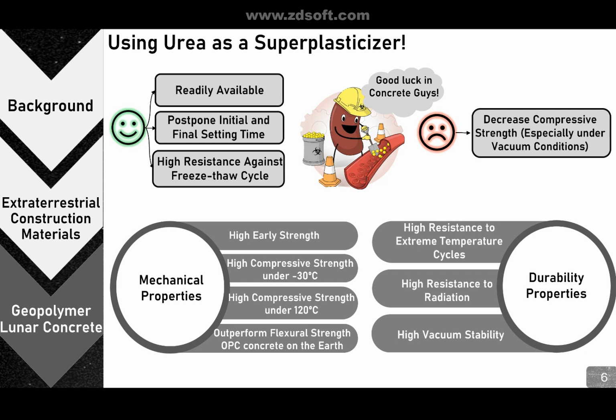There are contradictory results regarding the effect of vacuum condition on compressive strength of geopolymer lunar concrete. Interestingly, Zhou et al. also found that curing geopolymer under vacuum conditions can even favor their compressive strengths due to the absence of the efflorescence effect.